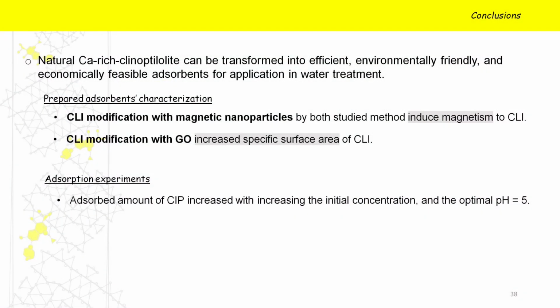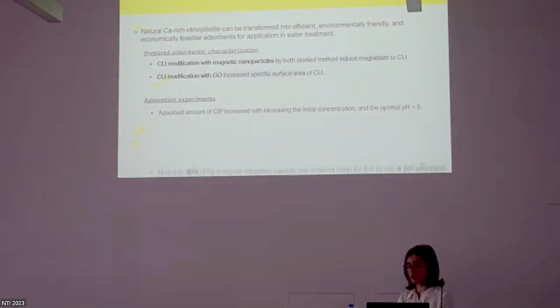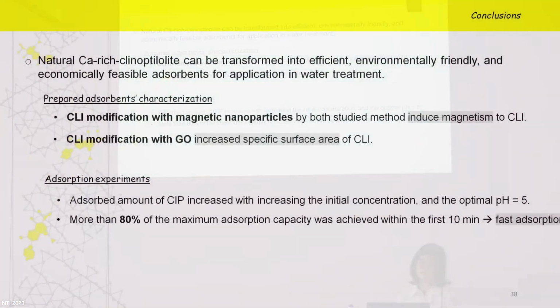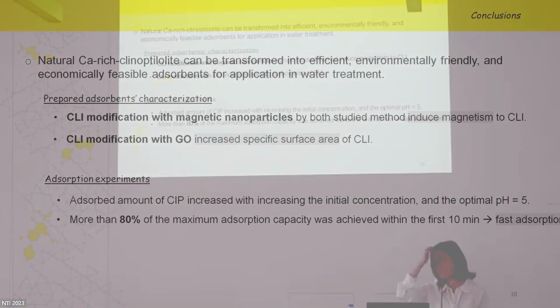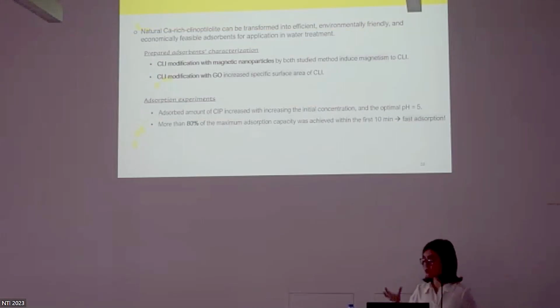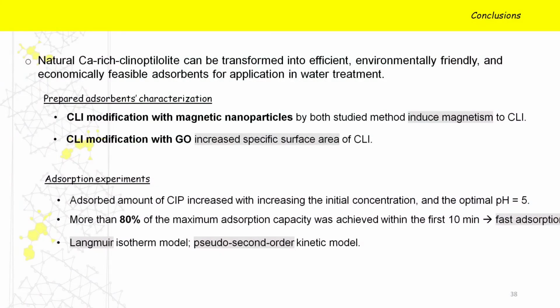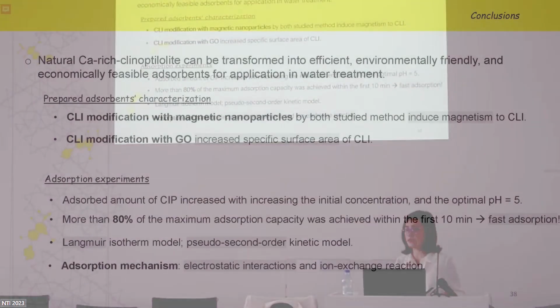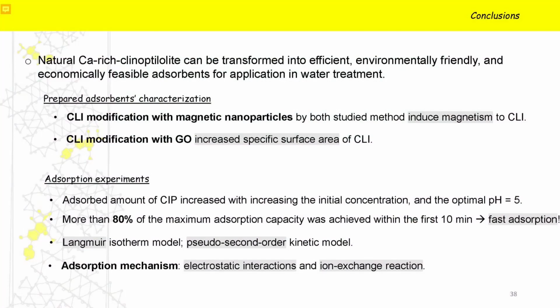The adsorption experiments show that the adsorption capacity increased with the increase in initial ciprofloxacin concentration, and the optimal pH is around 5. More than 80% of the maximum adsorption capacity was achieved within the first 10 minutes, which indicates fast adsorption. The adsorption process followed the Langmuir isotherm model and can be described by the pseudo-second order kinetic model. The adsorption mechanisms most probably include electrostatic interaction and ion exchange reaction.